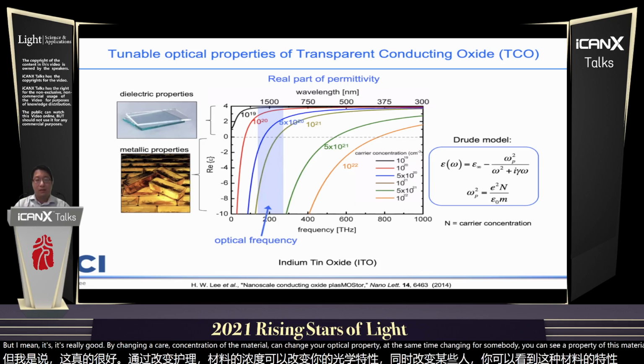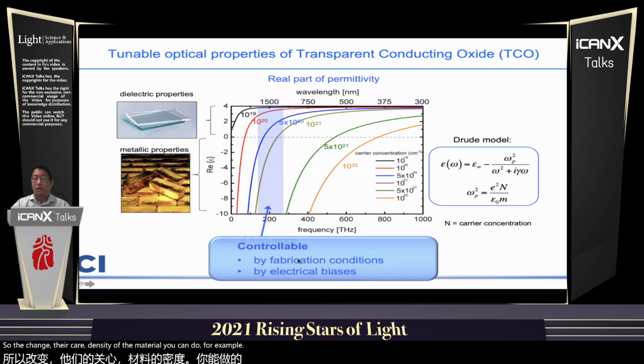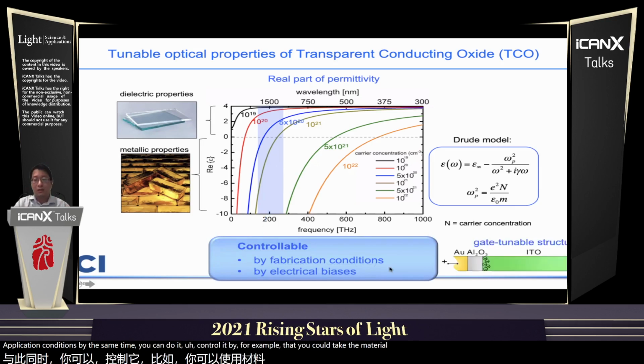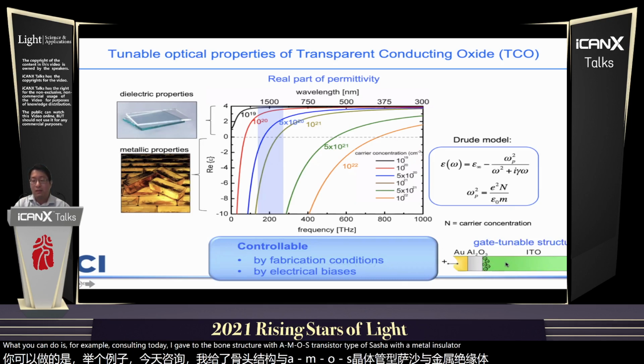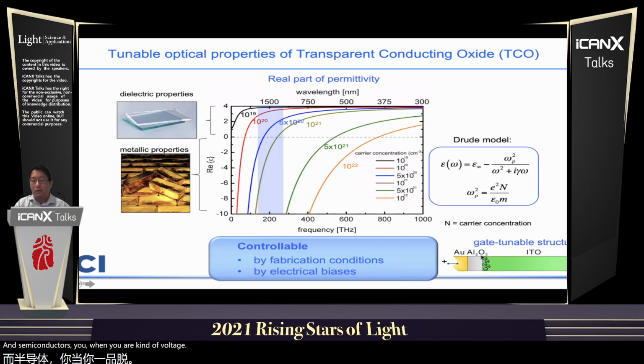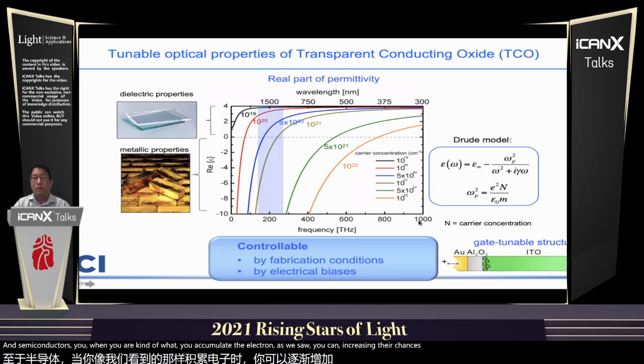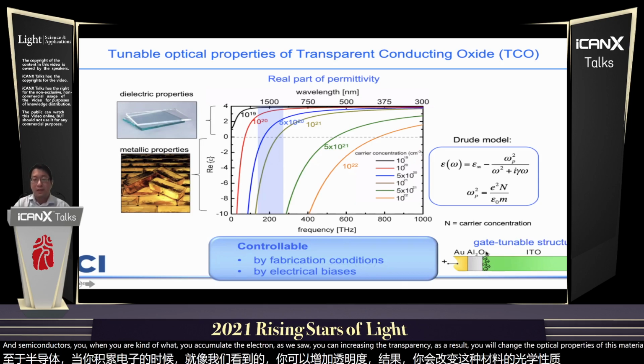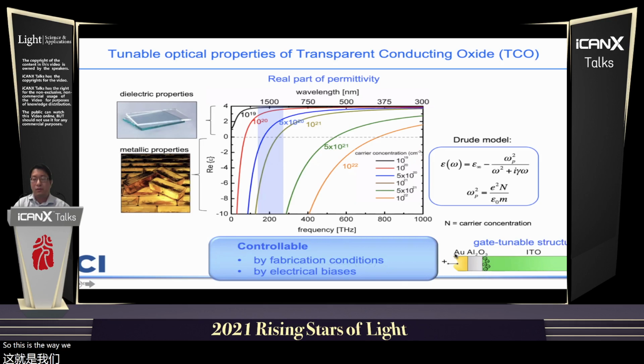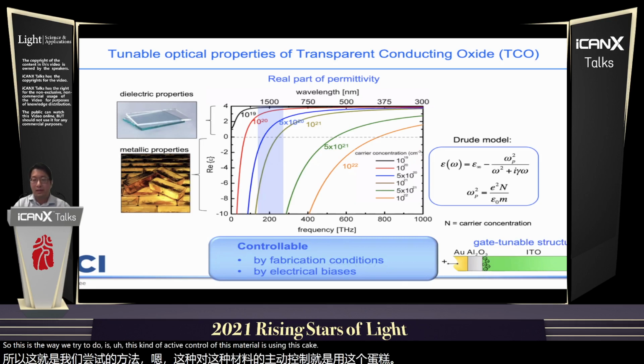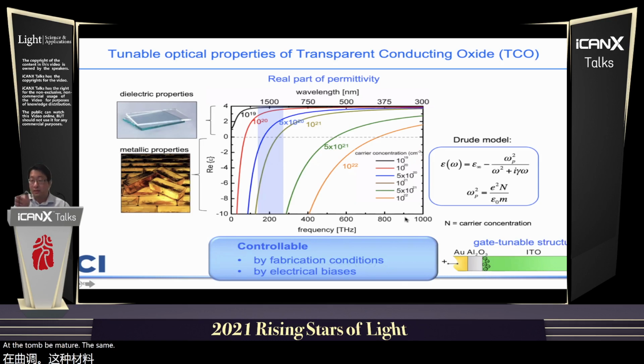To change the carrier density of the material, you can do it, for example, by fabrication conditions. But at the same time, you can control it by, for example, electrically gating the material. What you can do is construct a gate tunable structure with a MOS transistor type of structure, with a metal, insulator and semiconductor here. When you apply the voltage, you accumulate the electrons. As a result, you can increase the electron density, and as a result, you will change the optical property of this material. So this is the way we do this kind of active control on this material, using this gate tunable structure to tune the material and at the same time the ENZ property here.